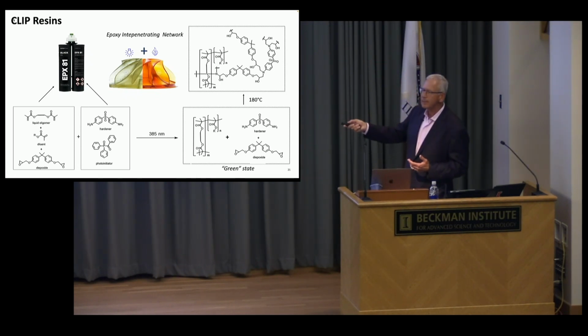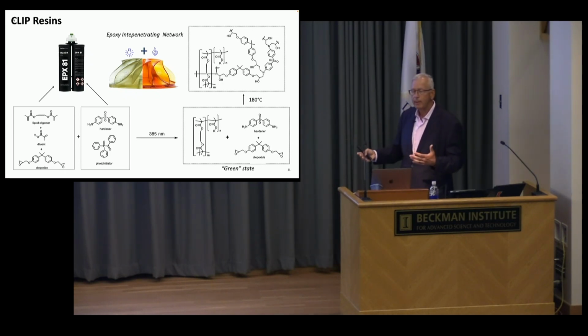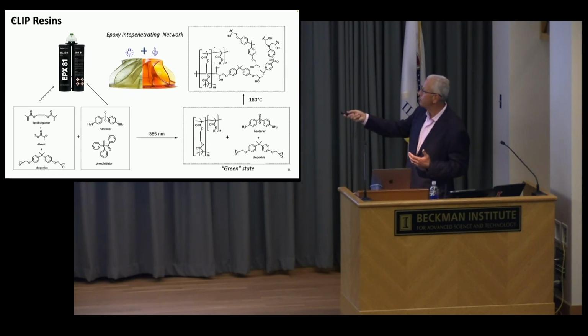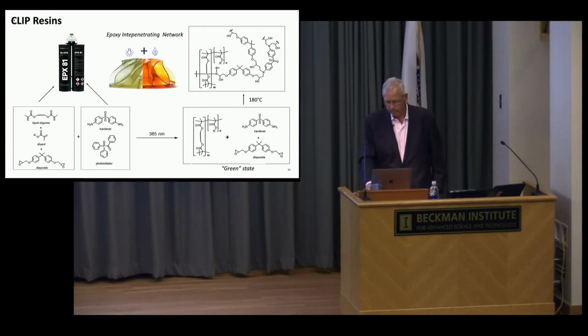And then you mix these reagents, you put them in the printer, you set the shape of the part. There's a little bit green color here. This is the green state. Doesn't have great mechanical properties, but it's sitting here with this other chemistry. And then we heat it up and drive it to full cure. And you can keep control of the stoichiometry and the functionality. You can get linear materials, you get cross-link systems. This is a great way to get a part. Now, when you do the light-based process, you typically wash it here, get all the excess resin off before you kick off the second stage, or you spin it in an environmentally dry process.